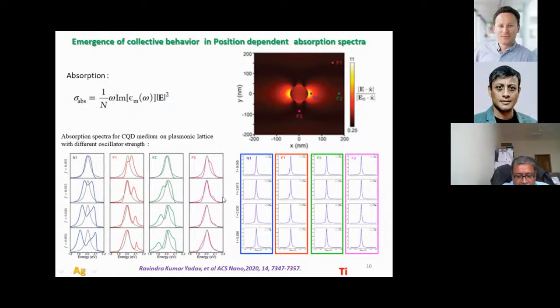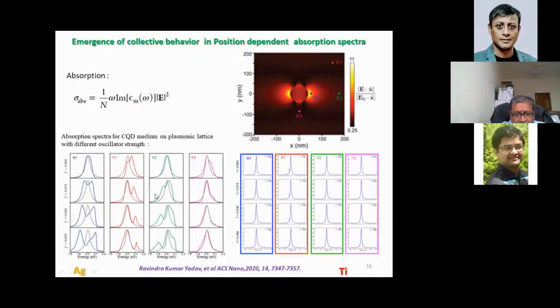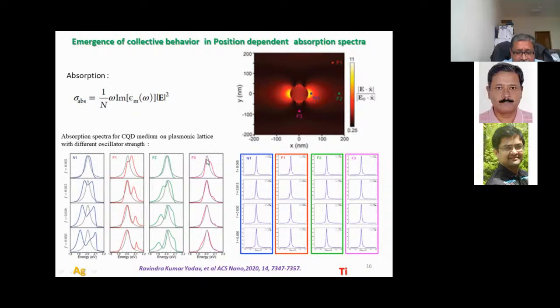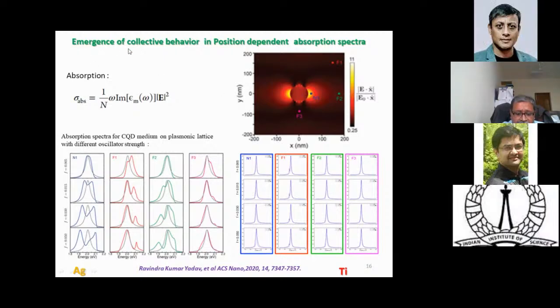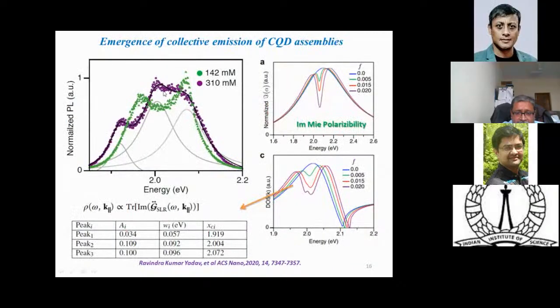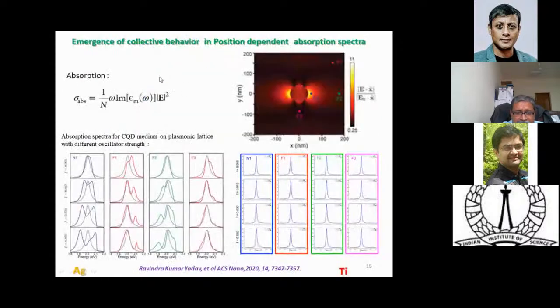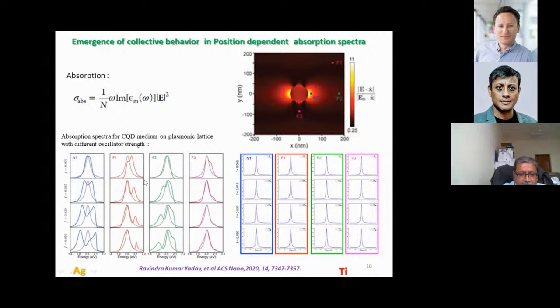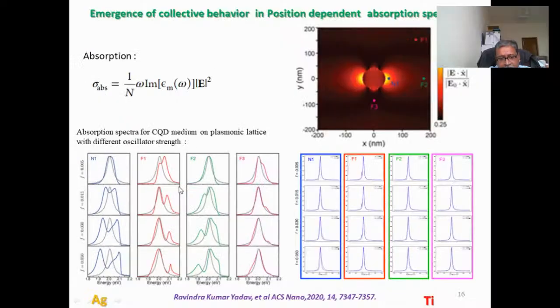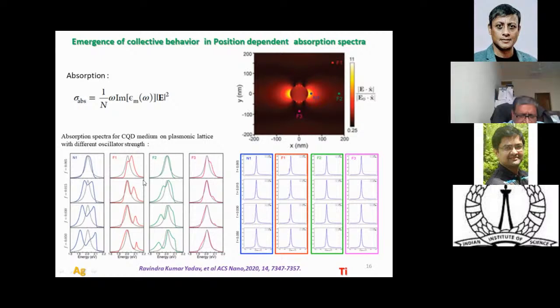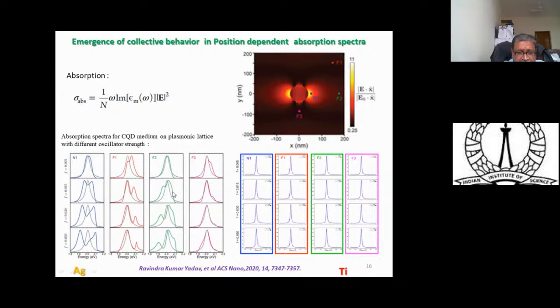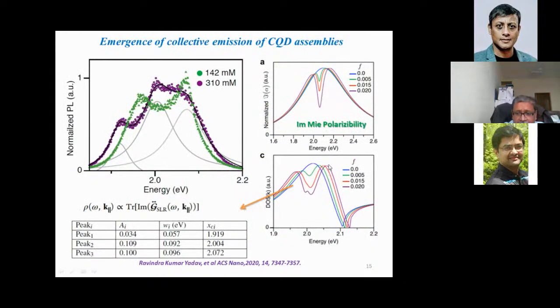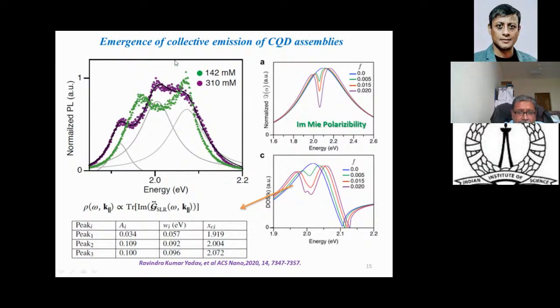So in other words, the long story short, we see that it is spatially dependent, and we say that this is a collective behavior which emerges in the system, and one signature is that it emerges at the position of the original one, and that it is driven by the SLR. Without the presence of SLR, you do not see this third peak emerging, and of course you need high concentration. So the enhanced absorption, because of the SLR mode, actually gives rise to the emergence of this collective emission mode, which has been observed in a different context in some other system. But here we are able to tune it, and also through the calculation show simultaneously the existence of all these different modes, both these polaritonic modes as well as this collective emission mode.